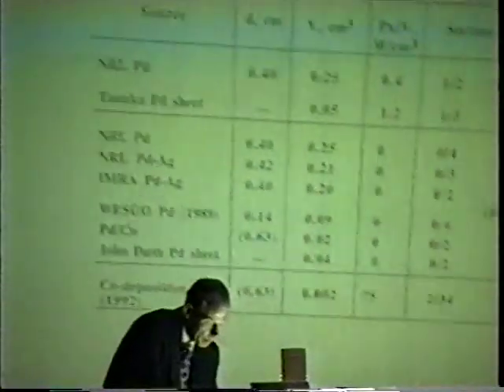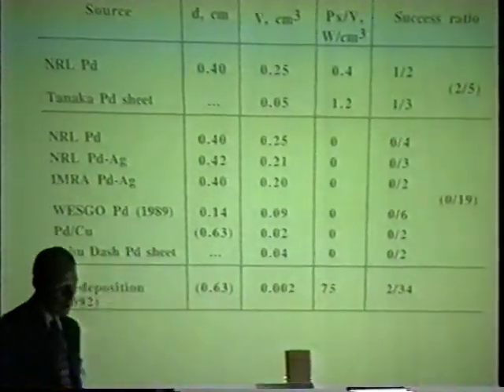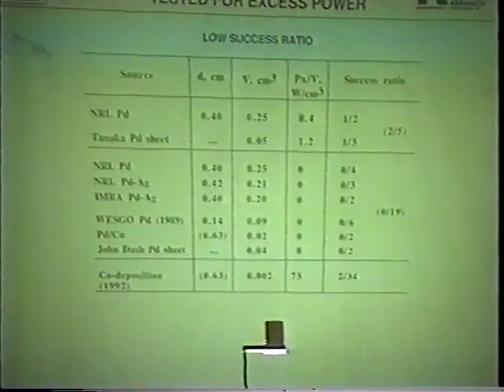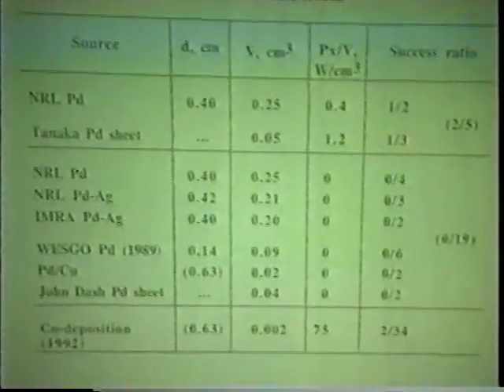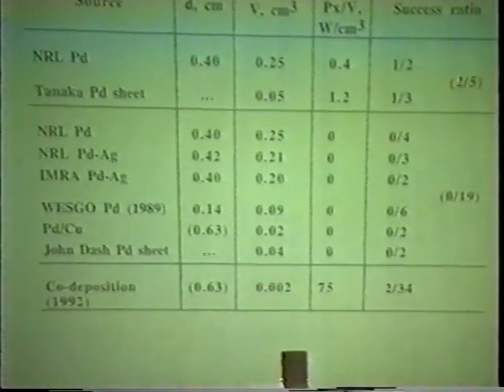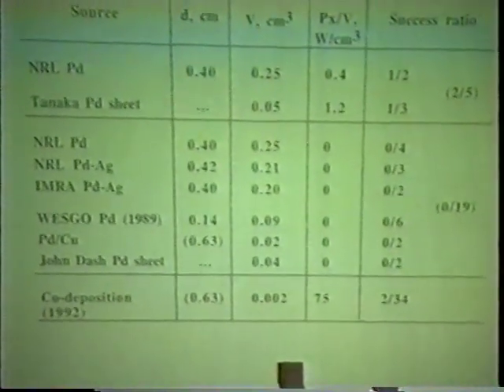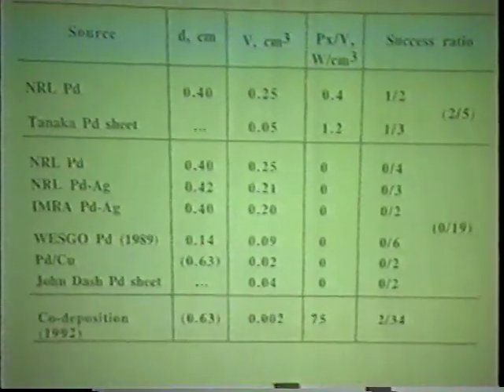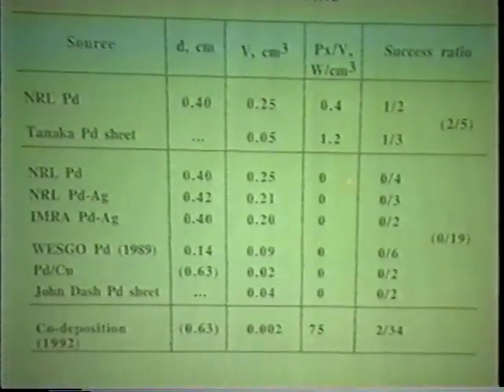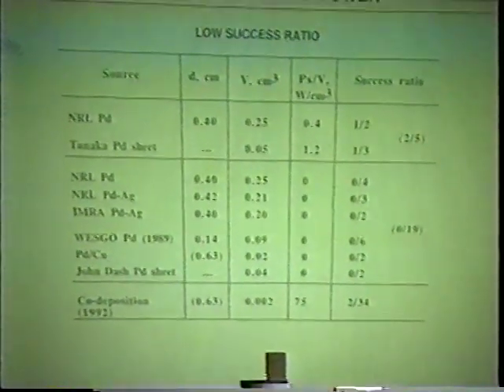But if you have bad material, we're going to the next one. If you have poor material, your success rate is poor. This is an NRL palladium, not the palladium sheet. We had some success. It's our intermediate, 2 out of 5. But we had a lot of NRL materials that did not produce any excess heat. They also showed poor loading studies.